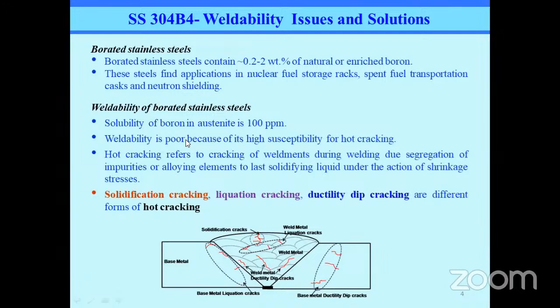So generally, in any austenitic stainless steel, the basic weldability issues will be hot cracking, distortion, etc. Similarly, because we have more boron in this austenitic stainless steel, solidification cracking is a major issue. So this solidification cracking or hot cracking can manifest itself at different locations within a weld metal. That is, solidification cracks are formed in the weld metal itself, and liquefaction cracks can be found in the base material and previously deposited weld metal, and ductility dip cracking is found slightly away from the weld metal, in the heat affected zone, etc., in the base metal. So these are different forms of hot cracking that are found during welding of any stainless steels.